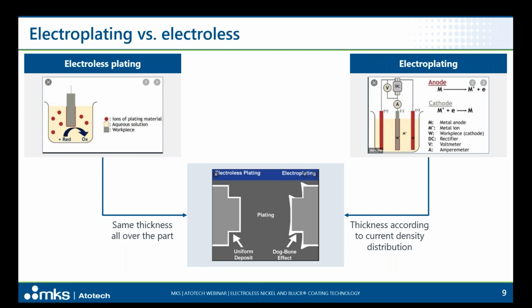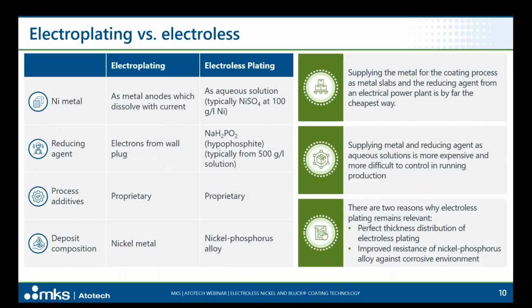In case of electroless plating, like electroless nickel, for example, we have a metal salt solution, in most cases nickel sulfate, with a concentration of 100 grams per liter nickel, and we have in our solution also a reducing agent, in our case sodium hypophosphite, and at a certain pH and temperature and in the presence of a catalytically active substrate, the nickel cations will be reduced and the nickel metal will be deposited on the substrate. What we observe here is that the coating thickness is the same all over the part, and this is one of the main advantages of the electroless plating.